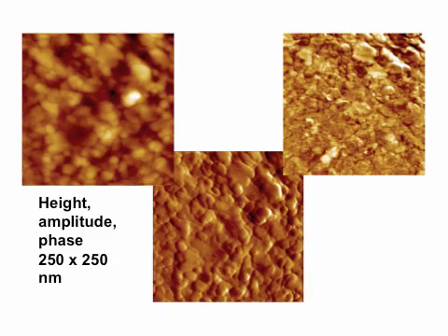What you see is that there is stuff that lies on the surface. Here you see a zoomed-in AFM picture. The square is 250 by 250 nanometer, and you see that there is some bumpy stuff on it. The best image you actually get is from the amplitude image, the middle image. They're not really ideal cylinders, right? They're a bit like broken roof tiles, a little bit. But relatively close. About 20, 25 nanometer, you get 10 of these things roughly on one length scale, so it kind of works pretty well.